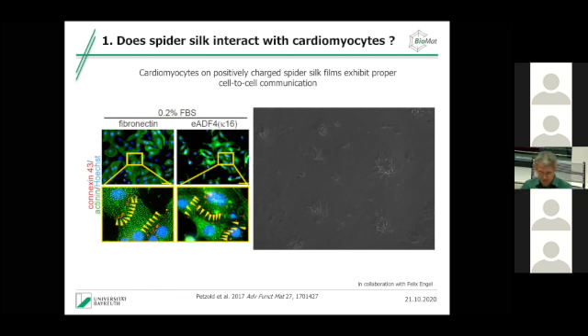So therefore, we investigated silk, because as mentioned before, we can do with silks whatever. We can even 3D print that. So the main question here was, do cardiomyocytes interact with silk surfaces? And to make a long story short, again, with our regular silk, they don't. Remember, no cell would like to attach to this silk. So therefore, we had to further engineer our silks. And what we did, we introduced positively charged amino acids. So on purpose, we changed the surface charge of the silk, which is typically negative, into a positively charged surface. The rest was the same.